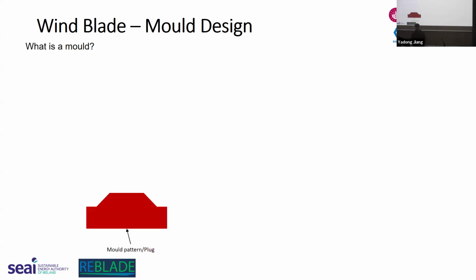So you usually start off with a mold pattern or a plug, which is usually in the shape of the final component that you want to manufacture. So the top surface would be the same as the wind blade skin. What you do then is you manufacture a mold, which is that gray component there on top of it, to take the shape of your component.